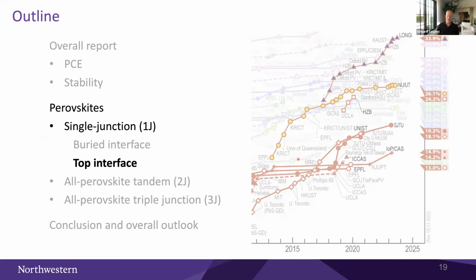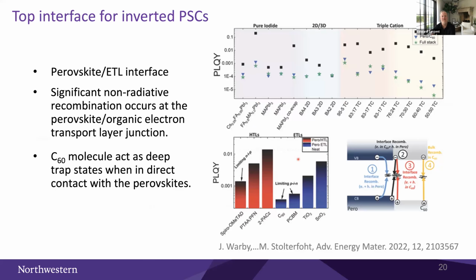I'd now like to turn to the top interface of the single junction devices and emphasize that clearly this is another crucial physical interface and chemical interface that we need to pay significant attention to. In particular, as we continue to rely on the C60 on top, we need to pay attention to quenching effects that originate when it's applied and to explore molecular strategies at these interfaces that can reduce the quenching that occurs when the C60 is put on.